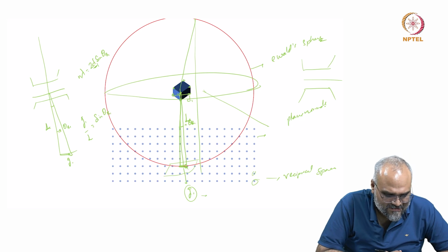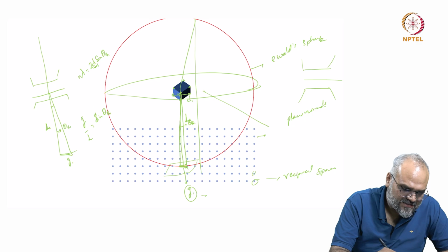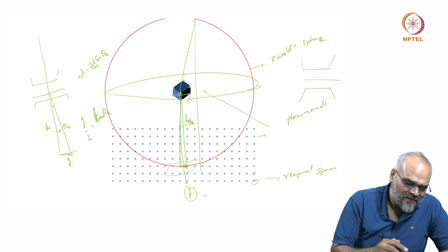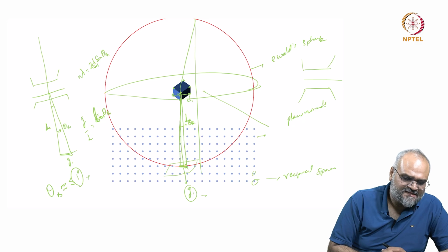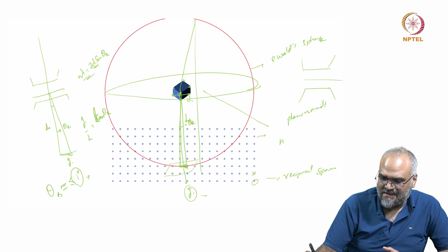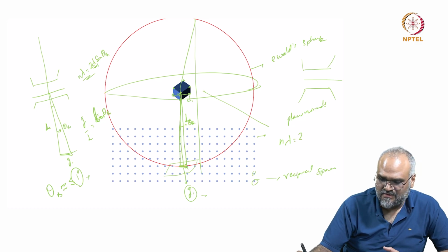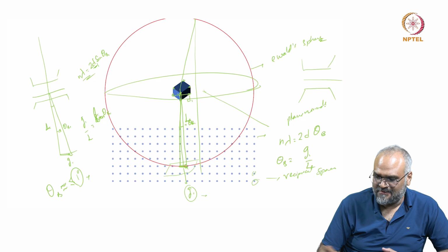But we know that for very small angles, I am sorry, this becomes actually tan theta b1, but when my theta b, the Bragg angle, is extremely small, less than 1 degree, this simplifies to an expression such that n lambda is 2d theta b, and from here I have theta b is g1 over L.